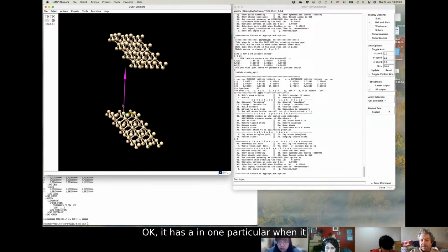In one particular place, when it calculates the Coulomb interaction, it uses plane waves on the grid, but this doesn't seem to impact the total calculation time much. But in VASP, it's important to remember this. So don't make this vector 100, say, if you don't need to. Just be careful. Always check.